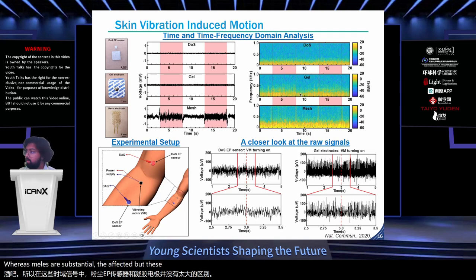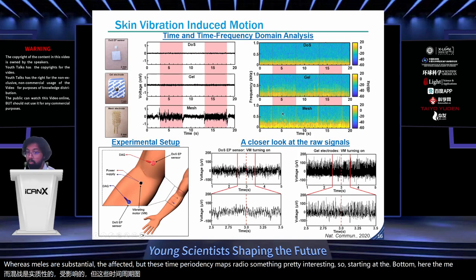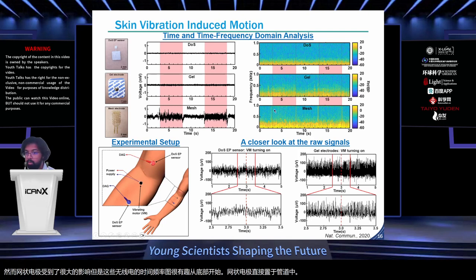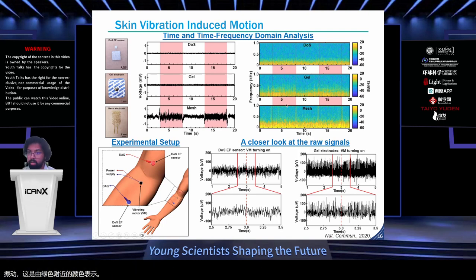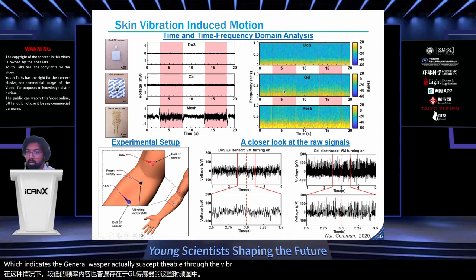But these time-frequency maps reveal something pretty interesting. Starting at the bottom here, the mesh electrodes were directly impacted by the vibration, shown by the green color near the 1 kHz line. Although the vibration was set to 1 kHz, we see substantial presence of lower frequency content between 150 and 500 hertz, particularly during the vibration period. This lower frequency content is also prevalent in the time-frequency map for the gel sensors, which indicates the gel electrodes were actually susceptible to vibration. And of course, the drawn-on-skin sensors show consistency across the entire spectrum.